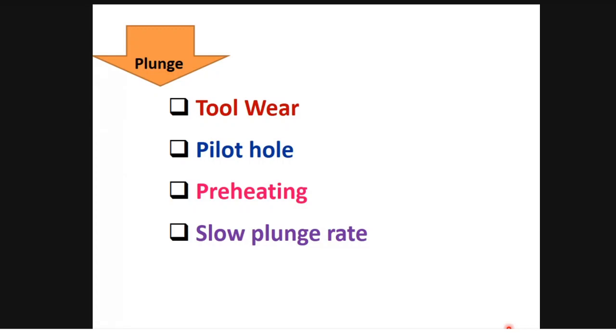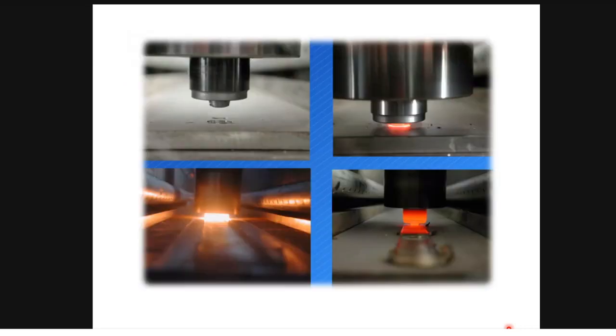Another thing is to go for a very, very slow plunge rate. If you do that, then during plunging, the tool wear can be minimized. And then, as I told you, you make a pilot hole and then use a slow plunging rate. And then you apply the ramp very slowly and then you retract the tool.